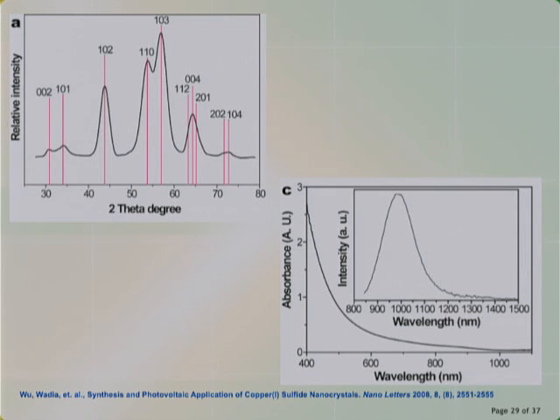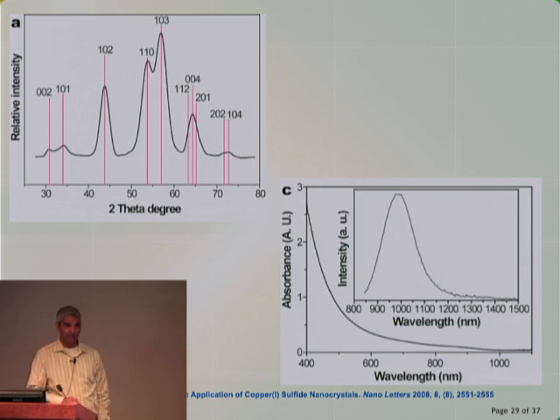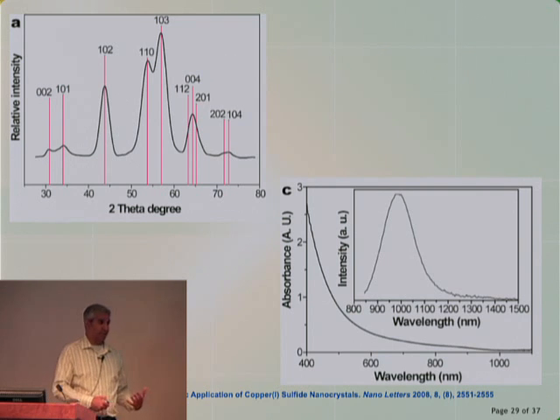A few more points on the results of this work. Some of you may be familiar with X-ray diffraction. It's a way to actually understand what your crystal structure is. For me, it's a way to know if I have any impurities. And again, when we started this project, we didn't find many or any papers that could isolate pure chalcocite. So this is a very good sign, because these red lines represent where the peaks should be in this diffraction pattern, and the black represents where our particles are. And again, it corroborates the fact that we have very pure material, one that's well suited for a solar cell.